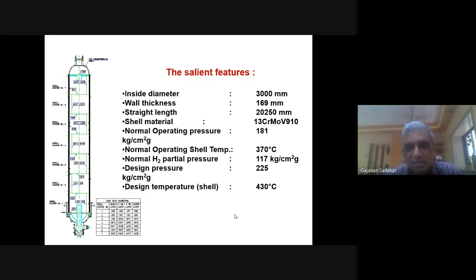Unfortunately, those guidelines are only for the hydrogen partial pressure. It's a function of the hydrogen partial pressure, temperature, and the different materials. It doesn't tell you, for example, if nitrogen is present, what is the effect of the nitriding. That is not taken into account. So there are various things, but still some guidelines are available. That's how material was chosen for this particular service.